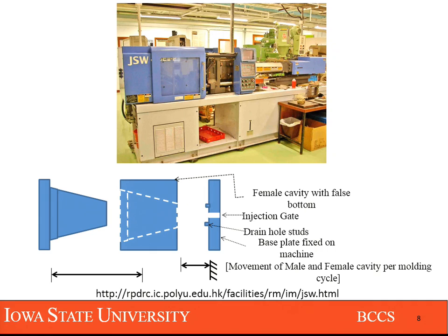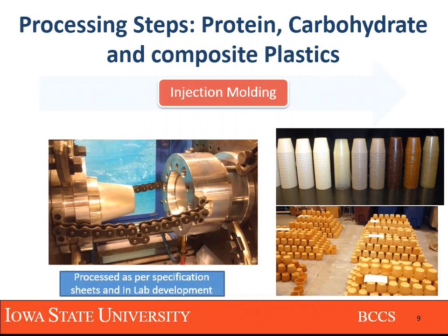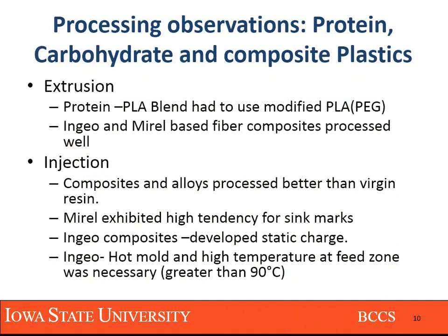That's what we had to do for the high soy content ones, but that was not the case with soy PLA blends or soy PHA blends, where typically the part would stay on the core side, which is what you would want so that you can use either ejector pins or stripper rings to go with a high production rate or mechanized process. And Dr. Gruel already used this schematic. This was the 3-piece mold which we used. We almost became Egyptians. We started building pyramids of pots, and that was basically our first round of 30 different materials.